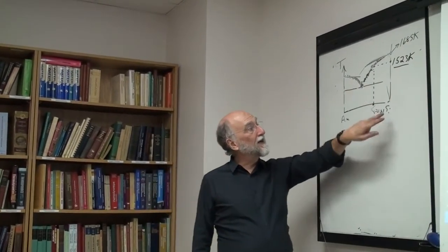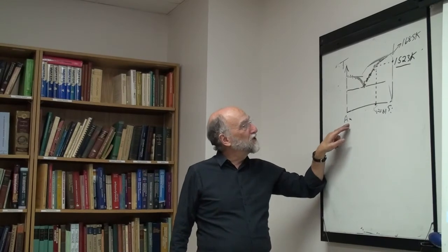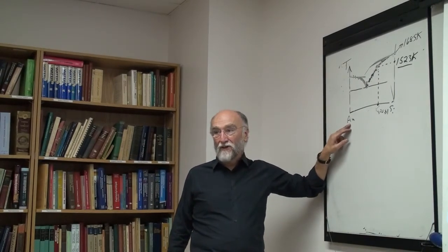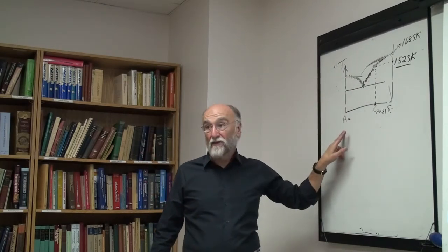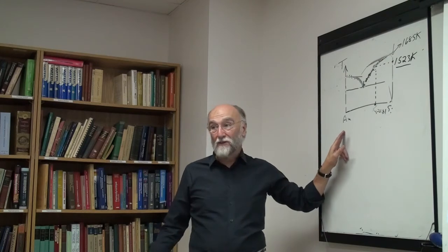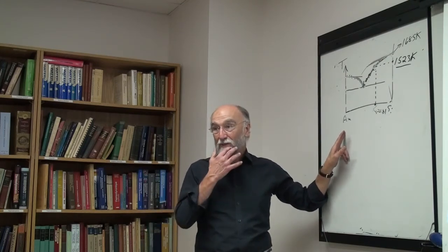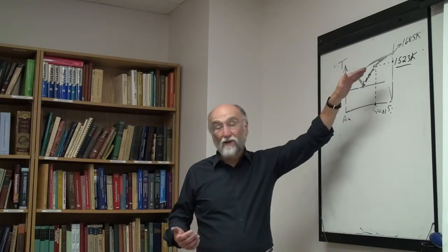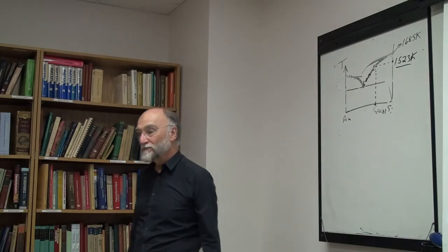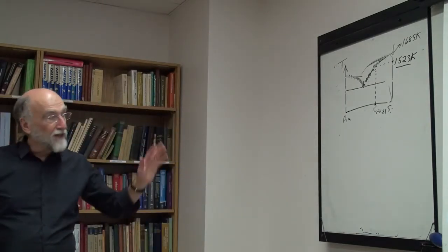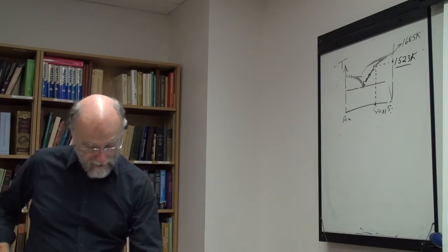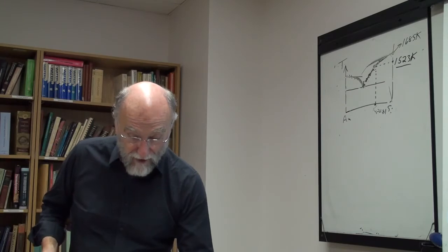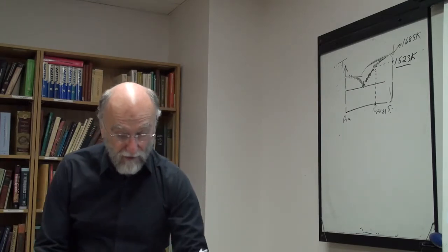Again, the other way to check it: say I want to get the heat of fusion of silicon. I'm not sure whether gold has zero solid solubility or not. Well, okay, do it with gold, do it with 2 or 3 other metals, and as you said, it should be totally independent of the solute. If it isn't independent of the solute, then at least one of them has got solid solubility. But if you do 3 or 4 solutes and they all give you exactly the same limiting liquidus, then you're pretty certain that you've got the same. So this is kind of the advantage of doing things that way. All right, I wanted to go a little further today, but I think this is a good place to stop.